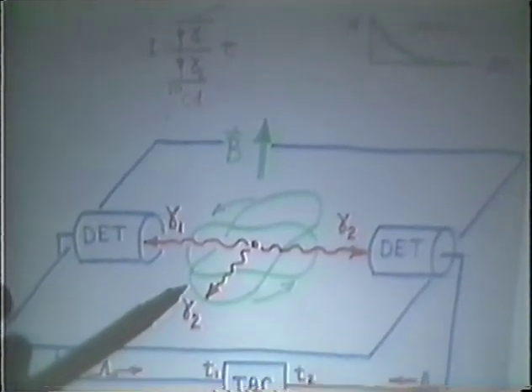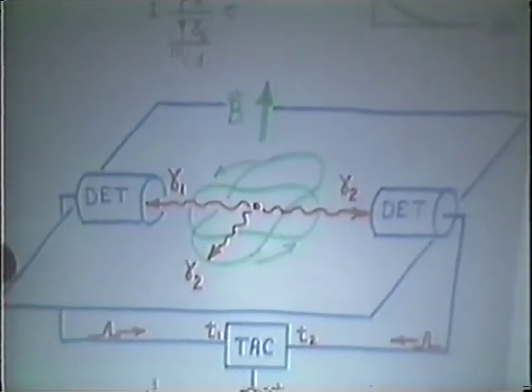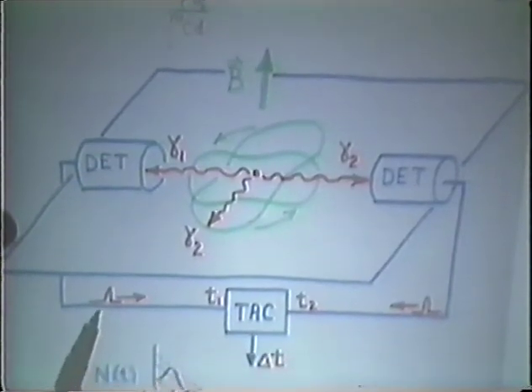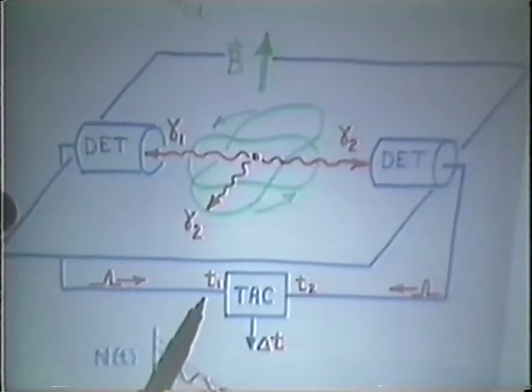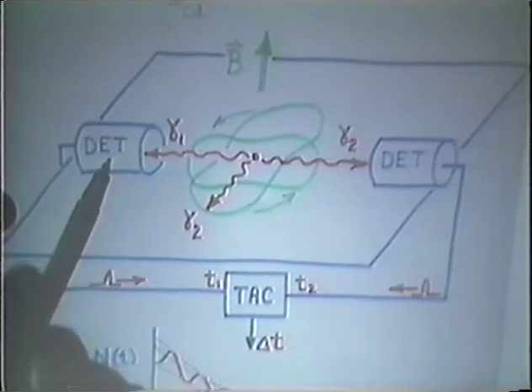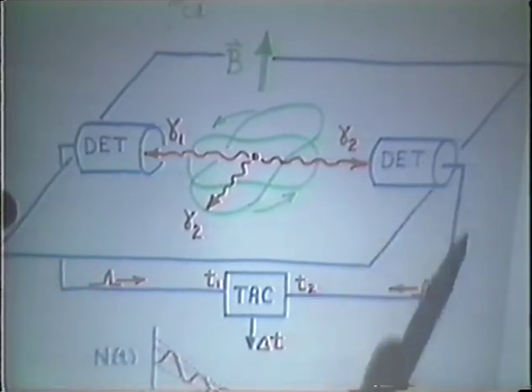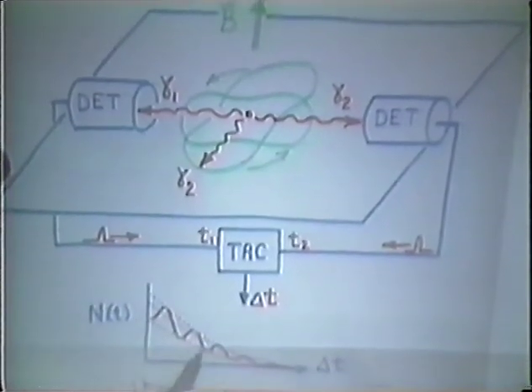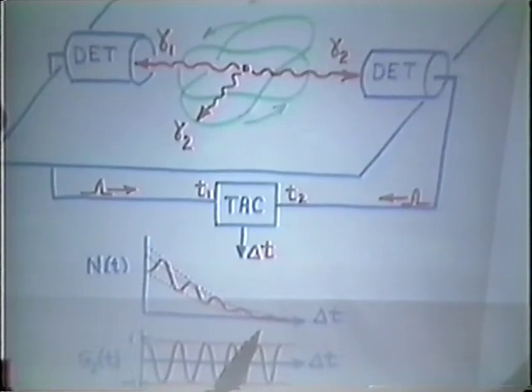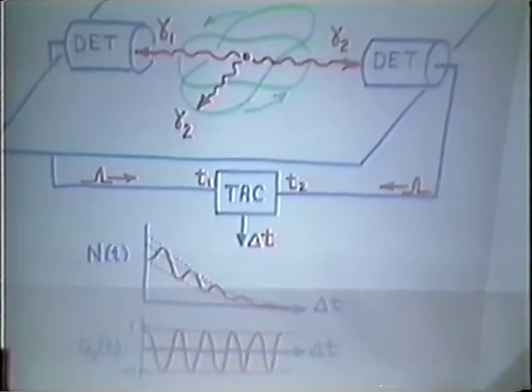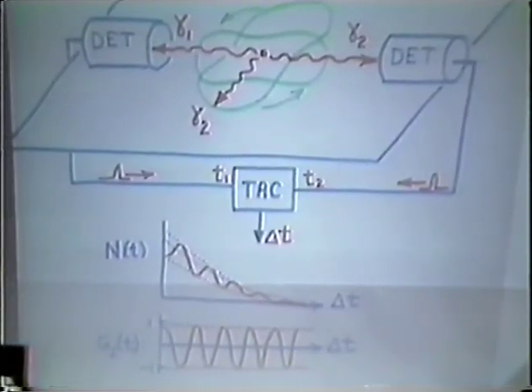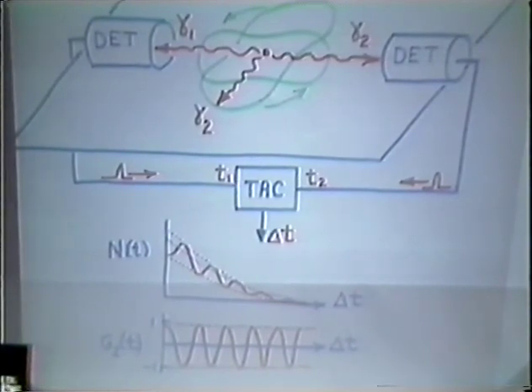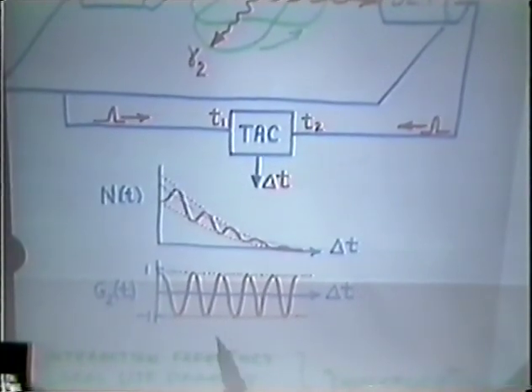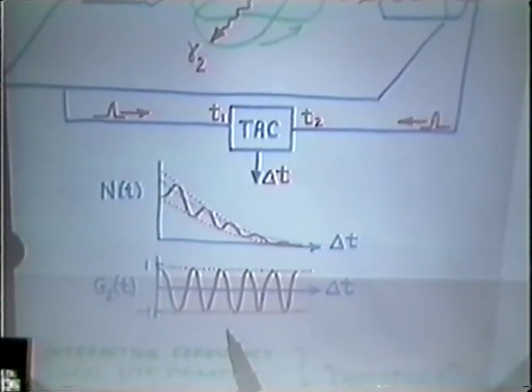anisotropy pattern will precess with the nuclear spins, and by histogramming the time differences between the arrival of a pulse in detector 1, a scintillation counter, and a pulse in the second detector, you'll see not only the exponential decay of the intermediate state, but it will be modulated by the anisotropy function. So we can extract that modulation function, which is called a perturbation function, and that will be characteristic of a particular lattice location for the probe atom in a solid.